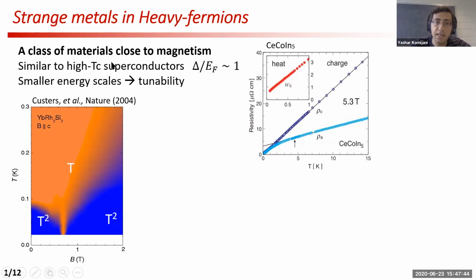are close to magnetism. They are similar to high-TC superconductors, with the difference that the energy scales are much smaller. And this means that we can use pressure or magnetic field to drive transitions in these systems. So a very good example is this ytterbium rhodium two silicon two, where with a magnetic field, one can drive a transition between two Fermi liquids. And in between, we have a fan of criticality with the linear-in-temperature resistivity.